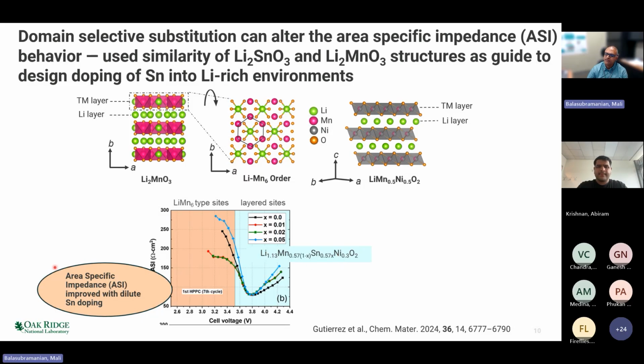So if you look at the area-specific impedance of this material, what you notice is that in this region, which is in blue here, or the background is in blue, you have a relatively low area-specific impedance. As you go down to this region, the low voltage region, the impedance rises, and for the undoped sample, the X equals 0 sample, the area-specific impedance goes up. But if you add small amounts of tin of the order of 0.01 or 0.02, where X is really small, what you find is that the area-specific impedance drops down.